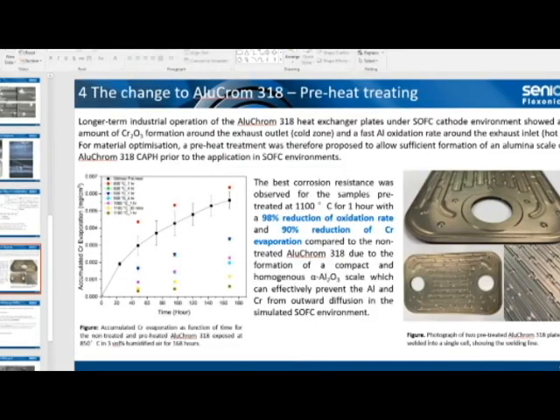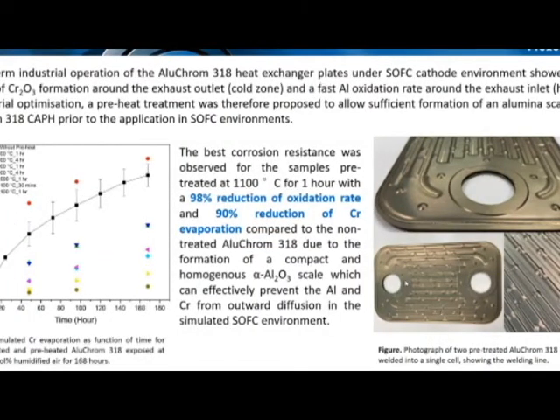So in order to optimize the material, we came up with one idea, which is the pretreatment. The pretreatment will allow sufficient formation of alumina scale on the heat exchanger surface before we put it into real application. So the pretreatment was conducted at different temperatures from 800 degrees to 1100 degrees with different pretreat times from 1 hour to 4 hours.